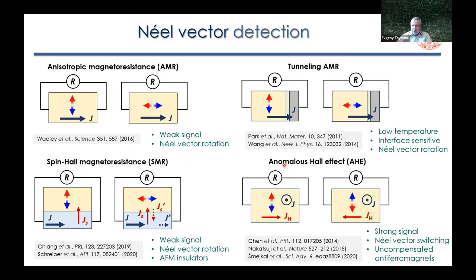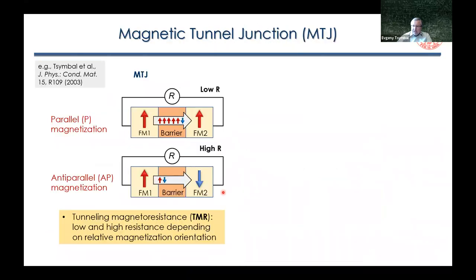which would be desirable for final applications. So in this regard, anomalous Hall effect is more advantageous. It has strong signal and is also sensitive to Néel vector switching. As I said, it's limited to uncompensated antiferromagnets. And another disadvantage of this is that you need to use a three-terminal device. So from the perspective of applications, it would be nice to have something more simple, to have a device which has basically two electrodes, similar to what we know in ferromagnetic spintronics. And this device is a well-known magnetic tunnel junction.